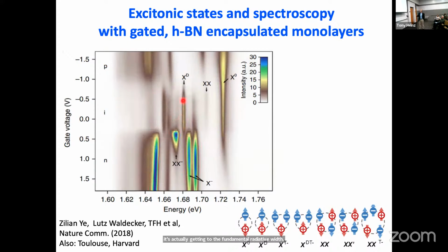So there are some spin forbidden dark states here, and this width corresponds to various non-idealities of interaction with phonons and inhomogeneities, but this width is actually clearly less than the width of the other features. So we're mostly seeing radiatively broadened transitions in the nicer samples. So we've begun to understand the different types of species that you can produce under different conditions of different charging and different excitation conditions.